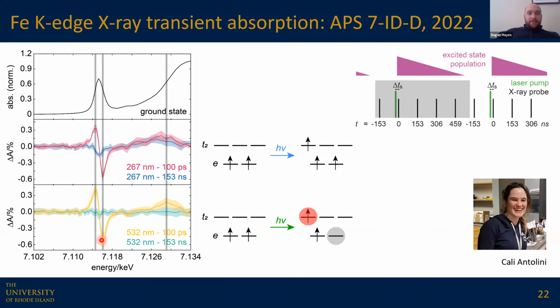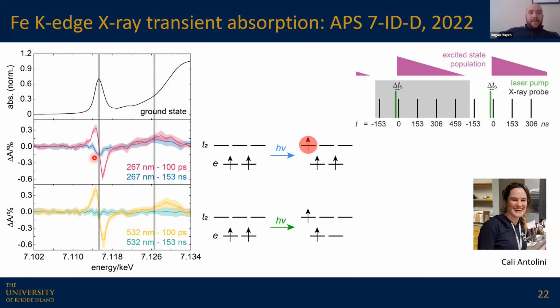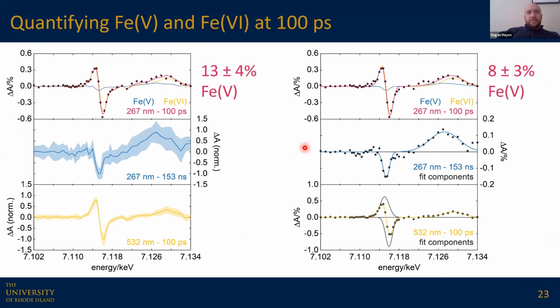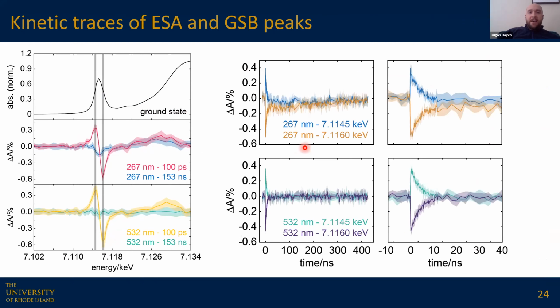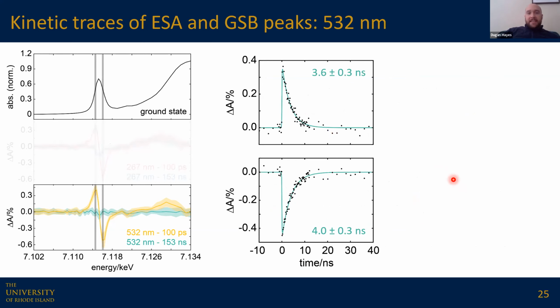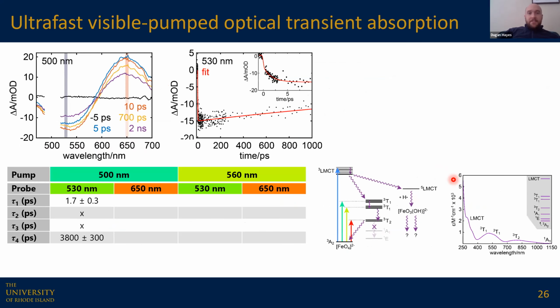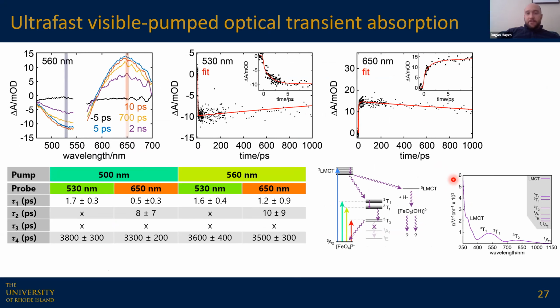And so these transient features correspond to moving an electron from the E into the T2 orbitals. So we get increased absorption on the red side of the pre-edge, lower absorption on the blue side of the pre-edge following visible excitation, and same following UV for the iron 6. But then at long times, what we have is this dip just corresponding to reduction of the iron 6 to iron 5 from the oxygen 2p electron. So we could do some linear combination fitting to see how much iron 5 and iron 6 we have, and look at these kinetics. We get very simple mono exponential kinetics following visible excitation with a time scale of about 4 nanoseconds that we can also follow using nanosecond optical transient absorption.